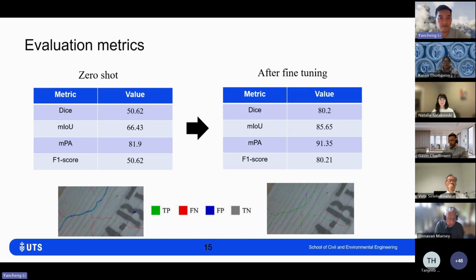So evaluation metrics, we have 4 metrics to investigate whether this algorithm is working fine. Higher value means better, so the highest value is 100. For all those parameters, we have improved significantly from zero shot to after fine tuning. The very important one is mIoU, which indicates the identification on the pixel level of the crack, and it is 85, which is very good so far.